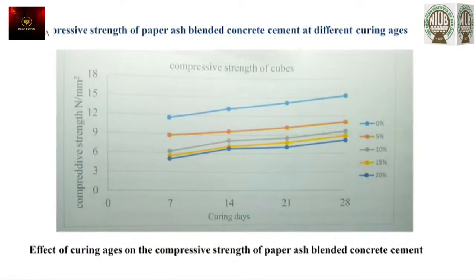Now, in the evaluation of the compressive strength of the concrete where the cement is replaced with waste paper ash at different curing ages, if you look at this graph very well, at the different percentage replacements, at the curing ages of 7 days, 14 days, 21 days, and 28 days, you could notice that with the increment in the curing ages, there is an appreciable increment in the compressive strength of this concrete. Now, for 7 days curing age, you could see that there is a slight increment, and likewise for 14 days, 21 days, and 28 days. So it tells us that there is an appreciable increment in the compressive strength of this concrete, where we have percentage replacements of waste paper ash as replacement for our Portland cement.